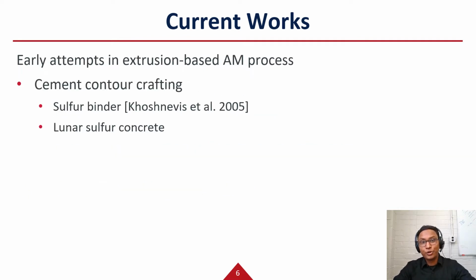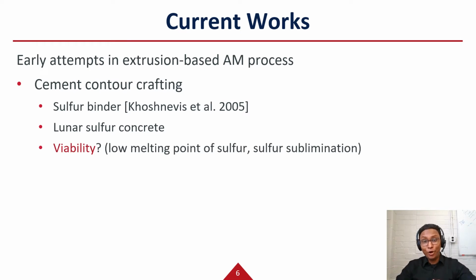An early attempt to construct lunar infrastructures via material extrusion was the cement contour crafting that uses the lunar cement prepared by mixing lunar regolith with a binding agent. The concept was an alternative to the hydraulic concrete that we use on Earth using the water-based cement. They proposed the use of sulfur as the binder to prepare sulfur concrete. However, the low melting temperature of sulfur limits the application of lunar sulfur concrete to only the dark regions of the moon.